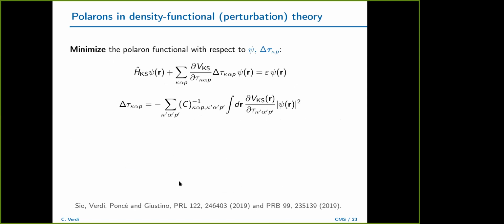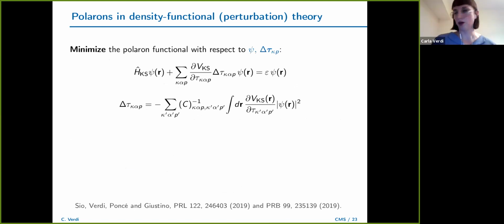Now, what we have to do now is to do the usual thing that you do in DFT. You minimize this functional, but this is a functional of both the extra electron and of the atomic displacement. So we minimize this functional with respect to both. And we introduce the usual Lagrange multiplier that takes into account the normalization of the electron wave function. So when we do that, we have these coupled equations.